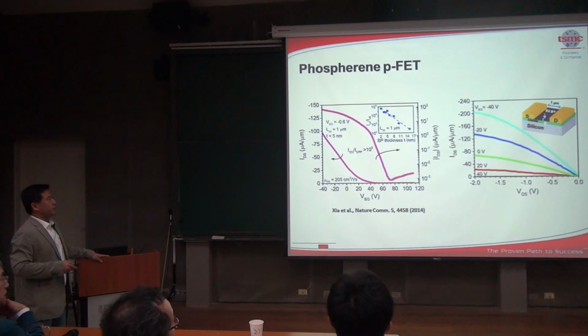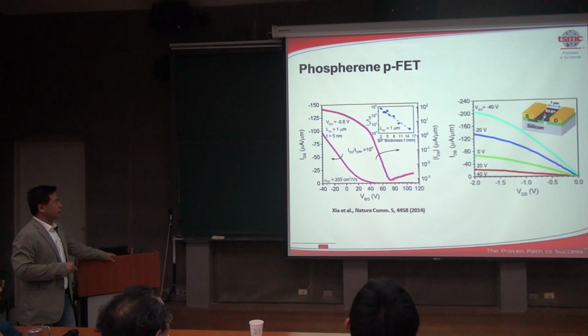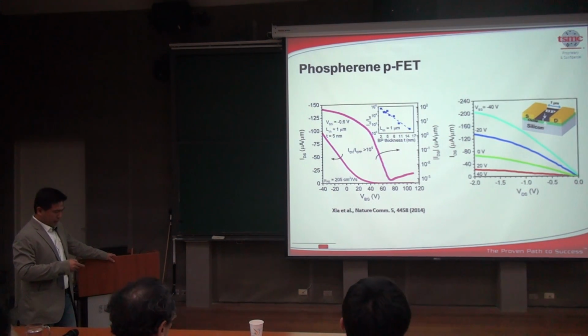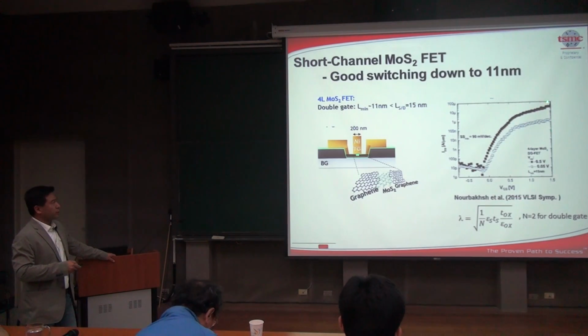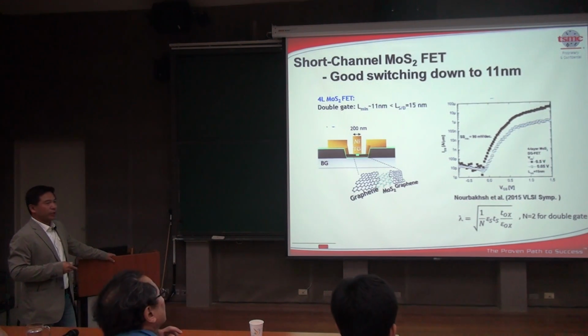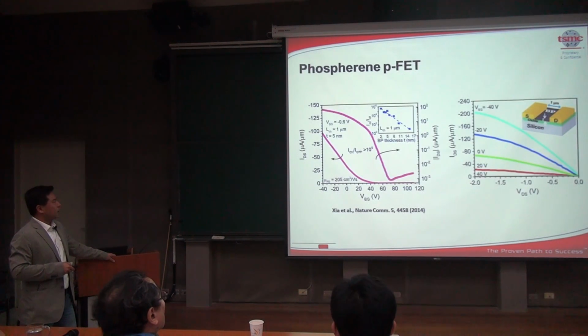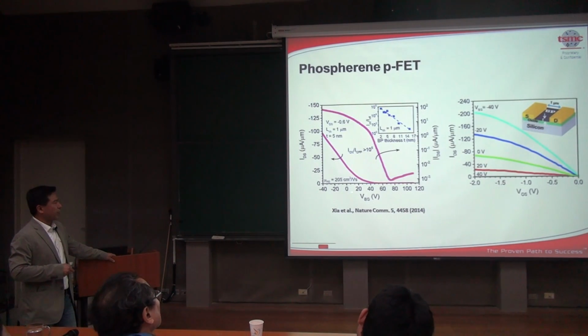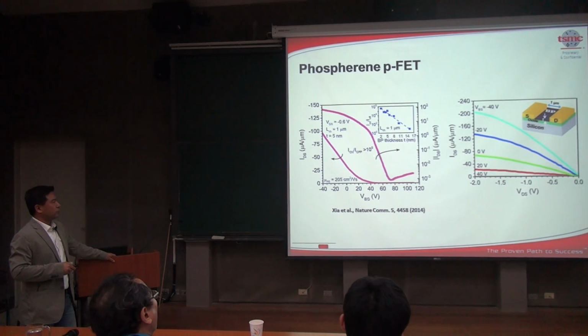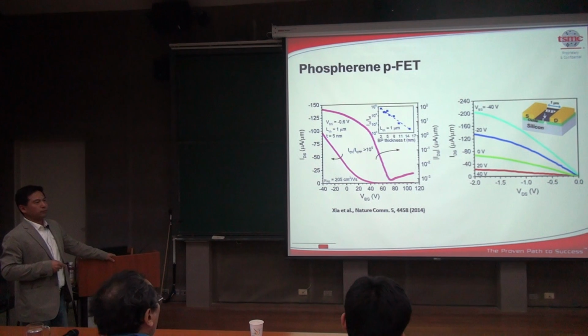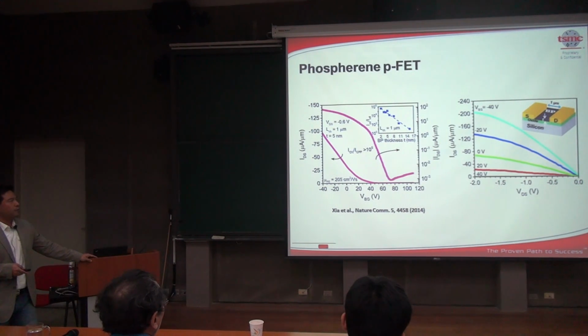And black phosphorus has a higher mobility. By the way, this MoS2 device, even though it has a good on-off ratio, has a mobility in the range of 10 to 20. That's quite low from the perspective of silicon. Black phosphorus has a relatively higher mobility, about 200. The on-off ratio is about 10 to the 5. So this is all a good starting point for consideration of a CMOS transistor.